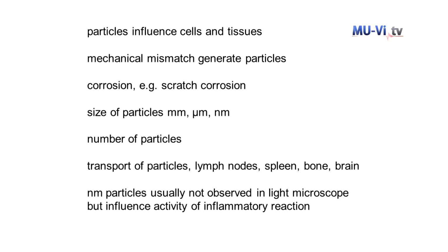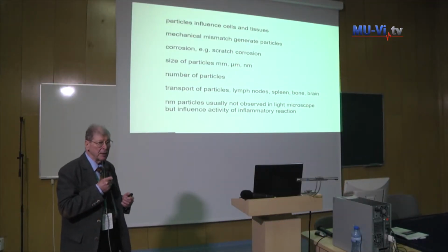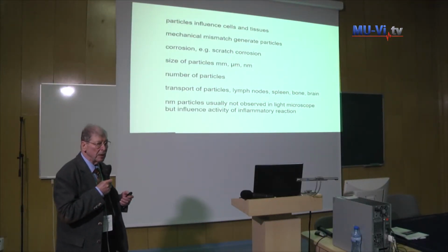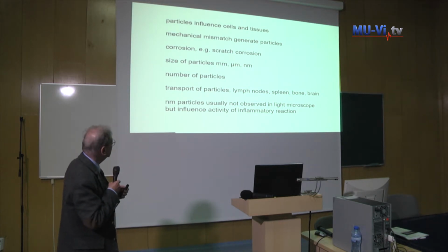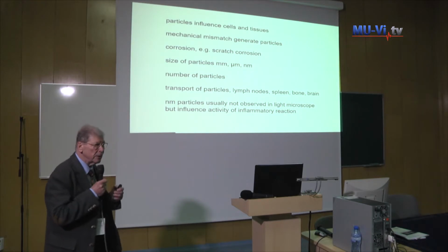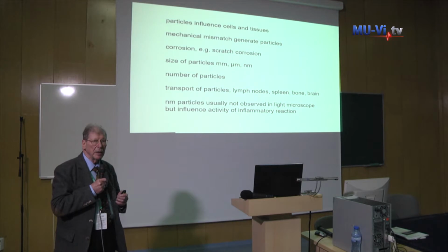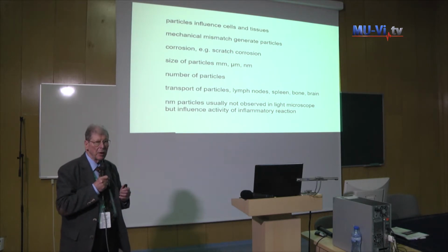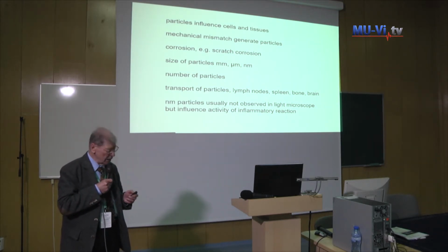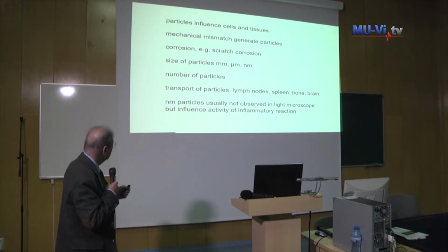The implanted stem is much less resilient than the bone, and this mismatch makes the interface in such a way that there are scratches, and the release of particles is not avoidable.